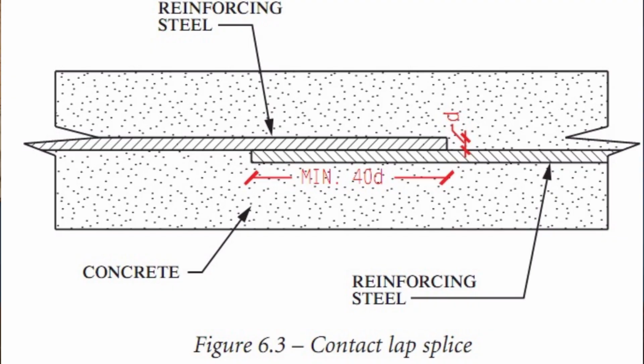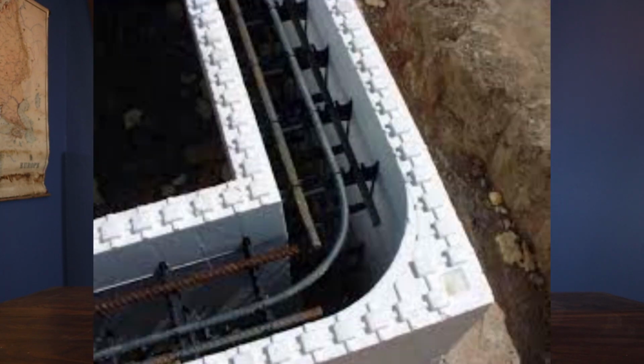Also, your walls are going to be a little bigger probably than what your typical stick of rebar is going to be. Most of the time it comes in 20-foot lengths, meaning that you're going to have to overlap those joints. The typical rule is 40 times the diameter is what that overlap should be. So if it's a number 4 bar, half-inch bar, it needs to be at least 20 inches of overlap to be adequate. And generally, you're going to overlap that bar as a contact joint and then just tie it together. With ICF, you can actually do a non-contact where you actually put it in the next nub, and that's fine too.